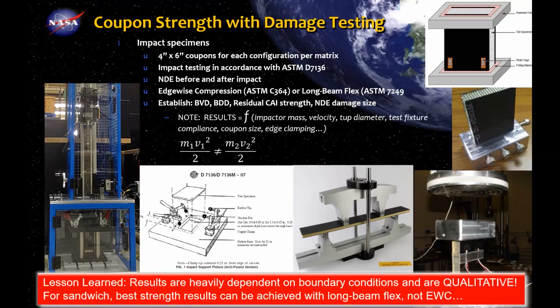Another quick point, edgewise compression is kind of an ASTM standard that everybody goes to that's associated with that drop tower standard. A fun fact, it is substantially better to utilize something like a long beam flex test that you see in the bottom middle. A 4-point beam bending test allows you to, say, impact one surface of a sandwich assembly and intentionally put only that surface into compression and keep the tension. And what that does is it eliminates all the complex buckling instability failure modes that can complicate the results. And in fact, it produces a much better statistical scatter that you can utilize for allowables development. Okay, next slide.